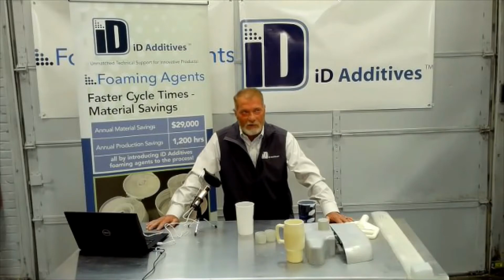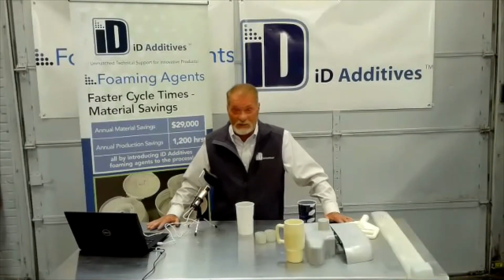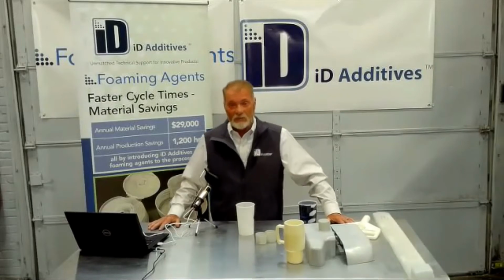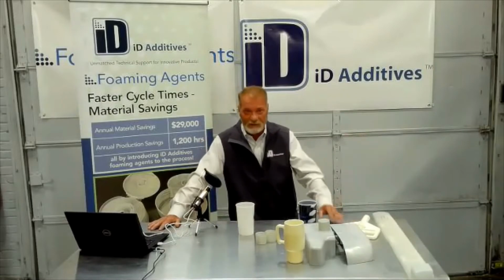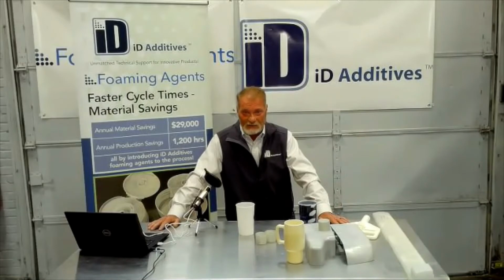We found the part temperature was 14% cooler when they added it, so they could see a cycle reduction because of the endothermic reaction. So definitely endothermics for injection molding and extrusion blow molding. They work really well.